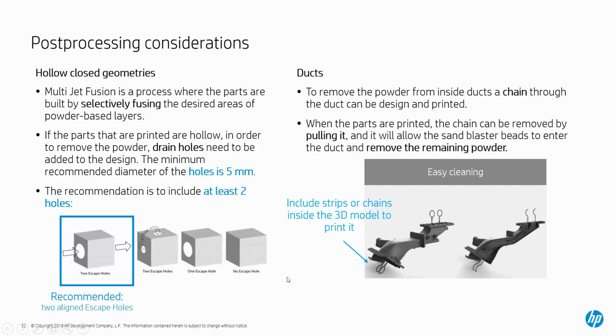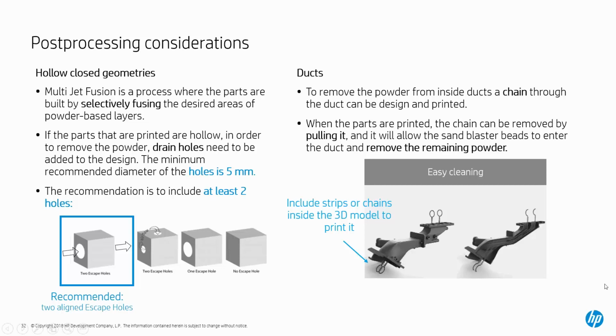And as I briefly mentioned, as you're doing hollowing parts, some of it is post-processing of how do I remove the powder out of the part, right? If I'm trapping the part for movement, if the part is going to be a hollow-walled part, as we talked about before, do I need to remove the powder out of it if it's a hollowed part? Maybe I need to leave the powder inside of it, which is fine. We don't need to talk about strategy of exit holes. But if I need to recover the powder inside of a part, this is what we're denoting here, is putting an exit hole or multiple exit holes in order to blast the powder out or drain the powder out of the part, right?